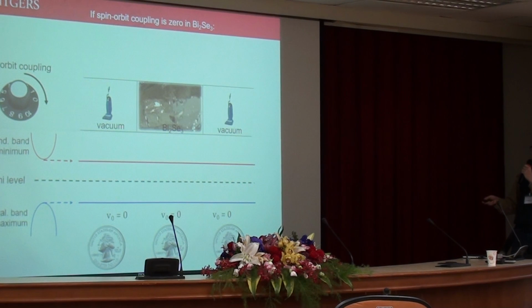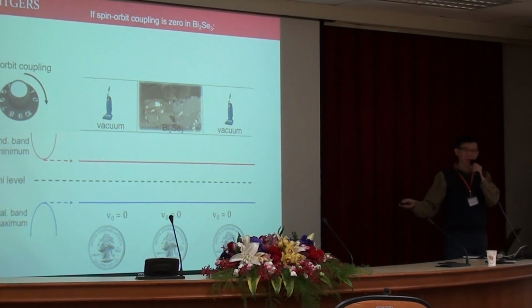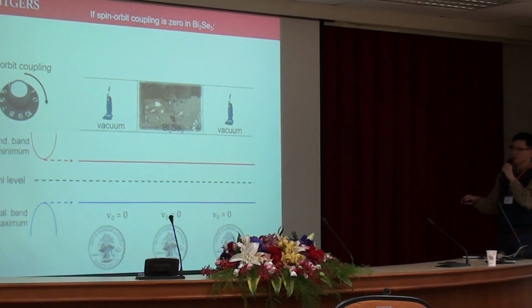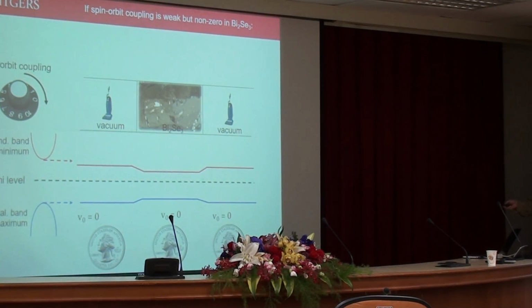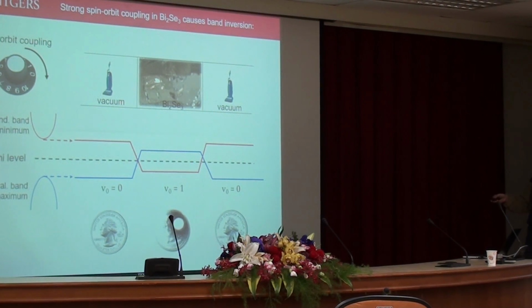A simple view is like this. Let's say this is vacuum or air. Then you have a band structure, the conduction band and valence band, outside the same. Let's say you start from bismuth selenide, and imagine it does not have any spin-orbit coupling strength. Then it is insulating, nothing happens, and there's no surface state. But as you increase the spin-orbit coupling strength, the band gap of this imaginary bismuth selenide decreases. If you increase further, at a certain point, the band gets inverted, and then you can see that there is a crossing at the surface. If the Fermi level is anywhere inside, then you always have to cross this band. If the Fermi level crosses the band, then it is metal, so you are guaranteed to have metal here.